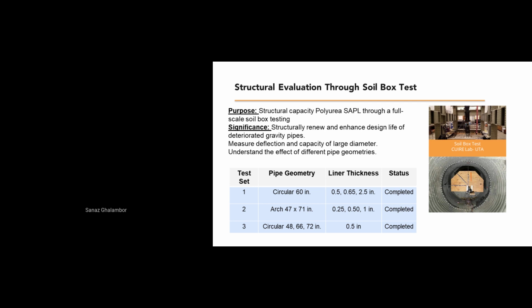Another important study that has been done was structural evaluation through soil box tests. For this, we ran the test on different pipe shapes, including circular and arch pipes, different sizes of pipe, and different thicknesses of the liner. So we did this test in 3 series. The purpose was to evaluate the structural capacity of polyurea SAPL. It is very important because we want to use this for structural renewal and enhancement of the pipe. So we wanted to make sure that this system can be used as a standalone pipe within a pipe without relying on the host pipe. It can carry all the loads needed.